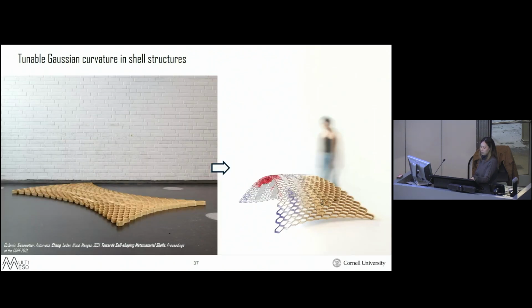From a flat shape, which we fabricated in 13 hours, it formed into this functionally graded shell structure within 1 week. And considering the complexity of the shell structure and also the functional gradation of the surface and also that fabrication of the 3D fabrication technology, it's quite fast for such a size.